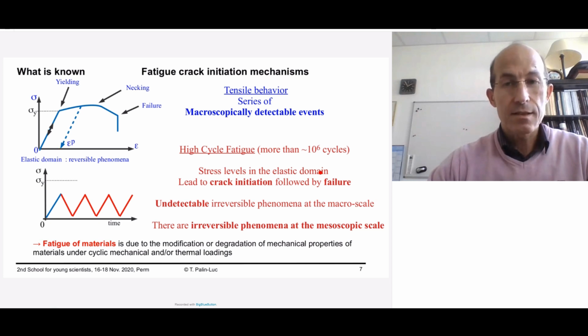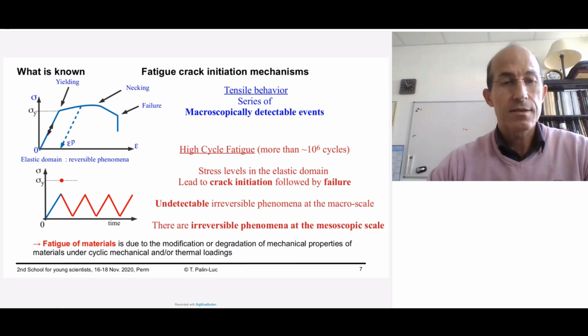But in high cycle fatigue, for stress levels leading to life greater than approximately 1 million cycles, the stress levels are below the yield strength of the material. And in this case, you cannot detect any irreversible phenomena at the macroscopic scale. But irreversible phenomena exist at the mesoscopic or at the micro scale. Consequently, fatigue of materials is due to the modifications or degradation of the mechanical properties of materials under cyclic loading or thermal cyclic loadings that create microscopic irreversible phenomena.